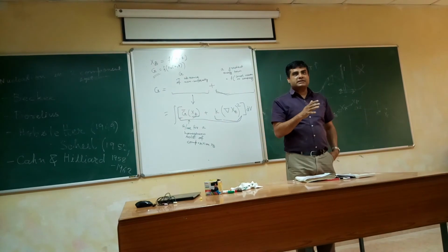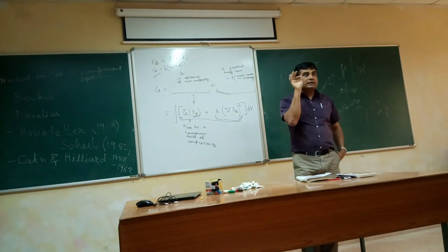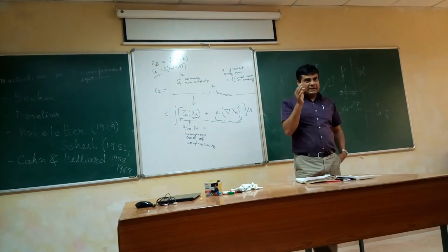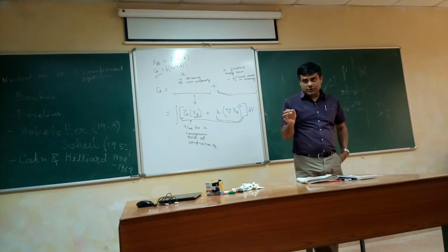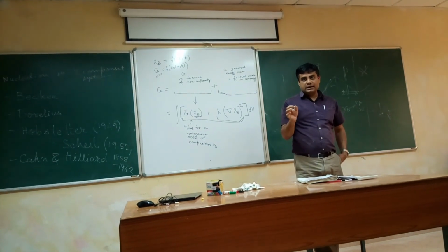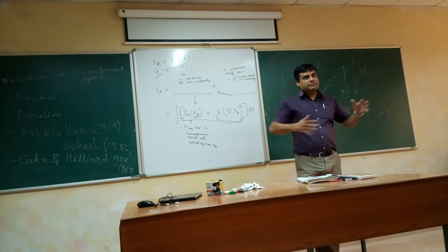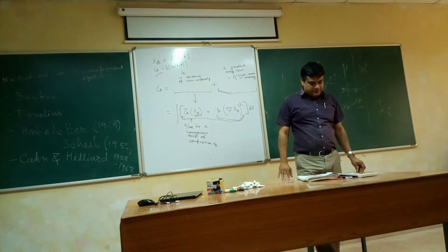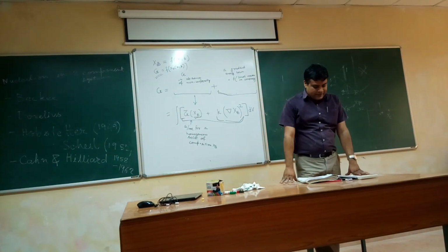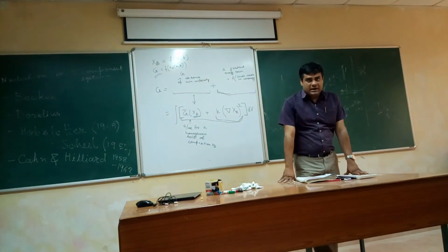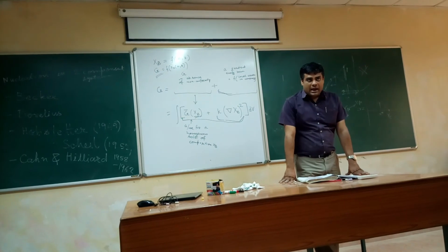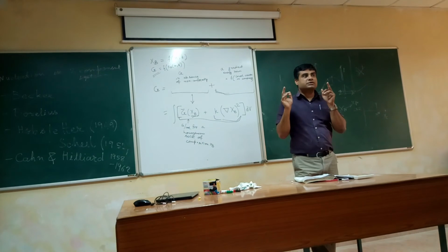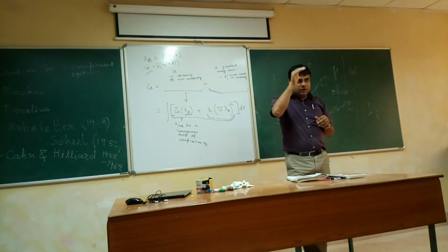At low supersaturation, when your matrix composition is very close to your spinodal composition, then interface width becomes very, very large, and interface becomes more and more diffuse until eventually no part of the nucleus is uniform, between your spinodal composition or below your spinodal temperature.